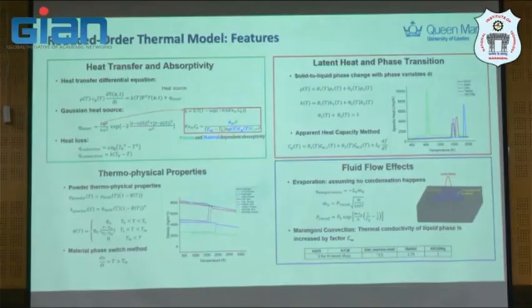It's not the surface heat source anymore. And heat loss follows the Stefan-Boltzmann relation. And then convection with this is normal, with heat transfer coefficients that you know and have to use a lot of the time. Latent heat of phase transition is actually a powder property as well.